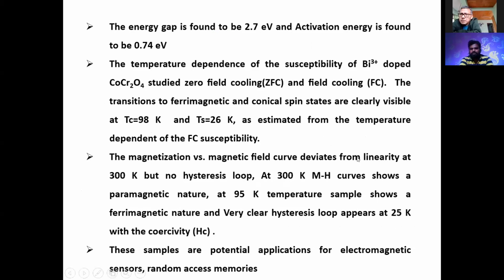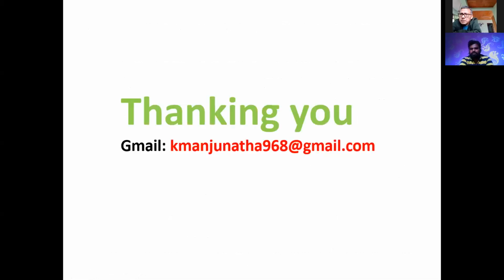It clearly shows that at 300 Kelvin the sample shows a paramagnetic nature, at 95 Kelvin it shows a ferrimagnetic nature, and at 25 Kelvin it shows a clear hysteresis loop with coercivity and remnant magnetization. These types of samples have great potential application for electromagnetic sensors and random access memories, etc. Thank you for giving this opportunity, sir.